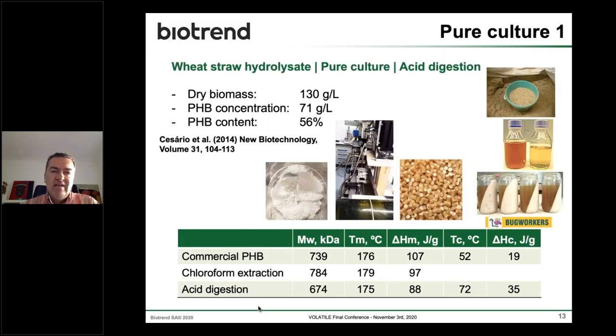So going to some specific cases, this was actually our first project in this field, and it was already more than 10 years ago. And we used wheat straw hydrolysate, which ended up being a really nice material to work with. We were able to obtain productivities which were very similar to the productivities that we would get from commercial sugars. And this was a very clean fermentation, if you will, and we were able to easily extract and purify the polymer without having much effect on the properties of the polymer.